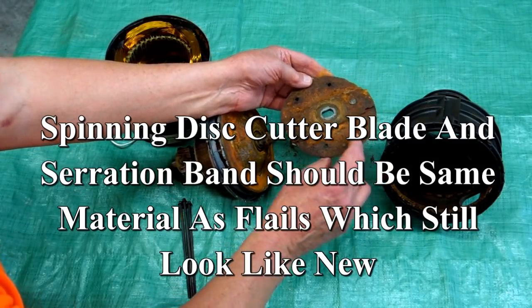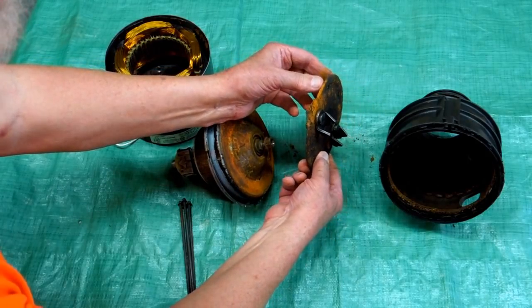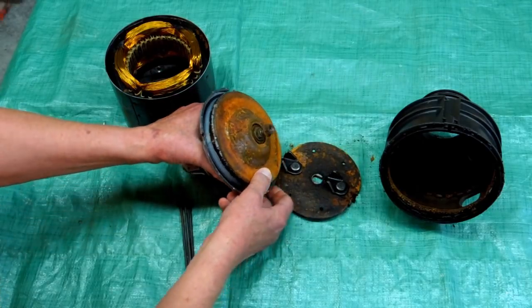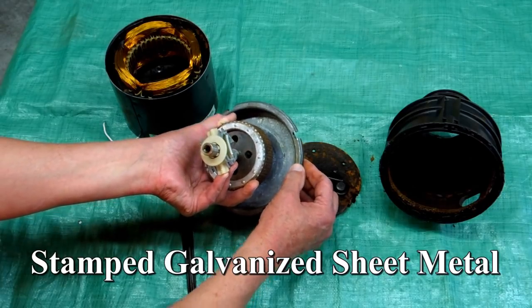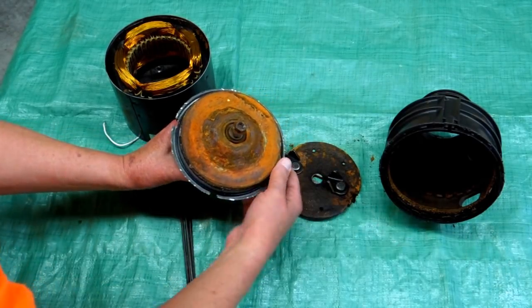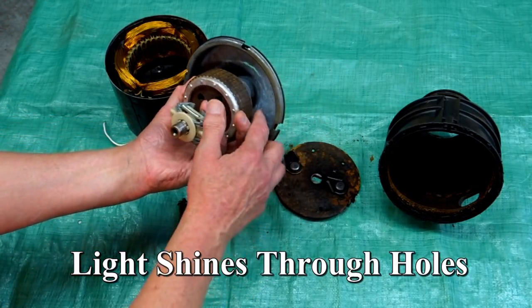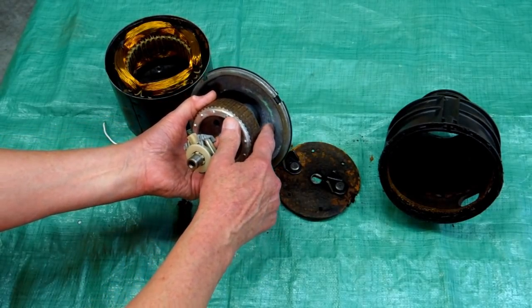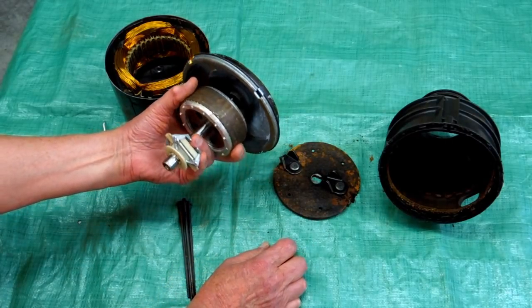This thing is nothing but a bunch of rust — it is pretty much deteriorated. There's still some material here but not much. The sad part is the bottom of this unit. It's just a piece of galvanized and not very heavy, and it has failed completely. You can see it has failed all the way around here. When it let go, it let go all at once, and that's where all the water was going underneath the kitchen cabinets.